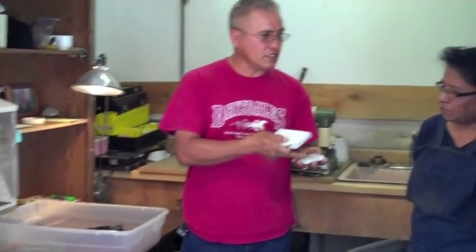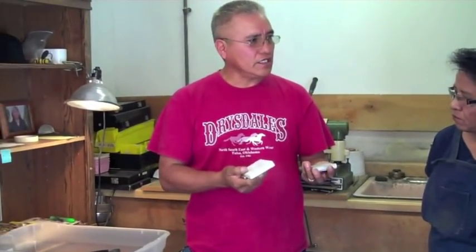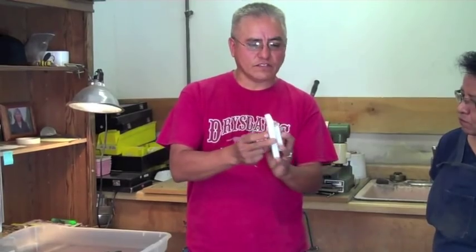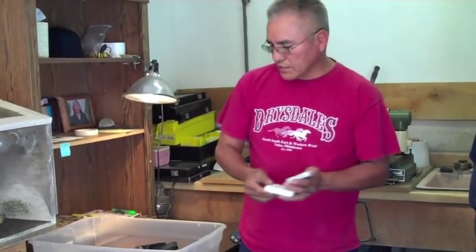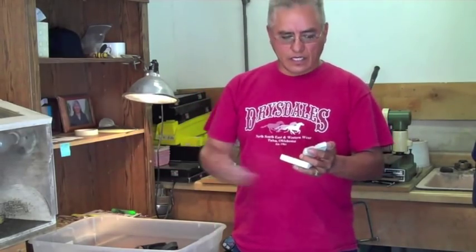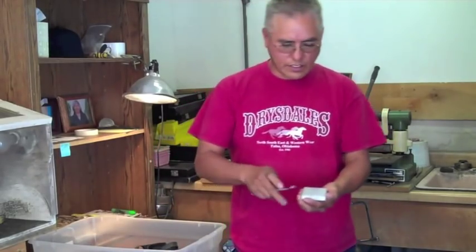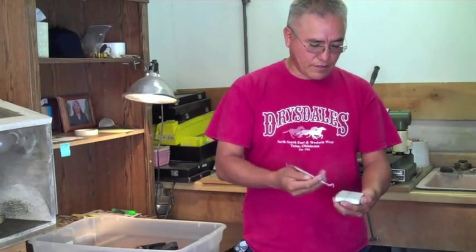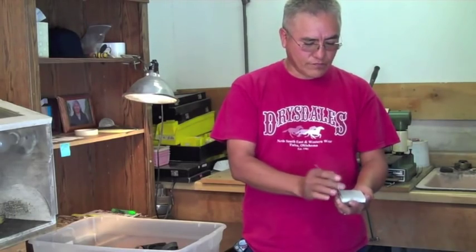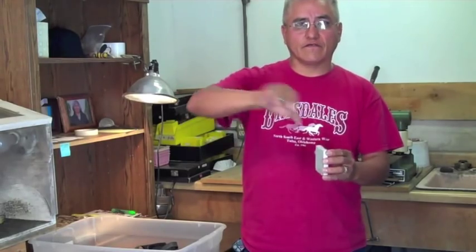You can actually heat this on this side and hold it in your hand, and that's how well the stone holds the heat. Putting it together with another piece of tufa stone like this and pouring the silver down in there is how you get your piece out of it. So you have to heat the silver, obviously. Yeah, you melt the silver in a crucible, and after the carving is done, you cure the stone. You have a smooth piece, and you also have the carved piece with a little pour spout and little air holes for air to escape. Put those together, tie them, and pour the silver down in there.